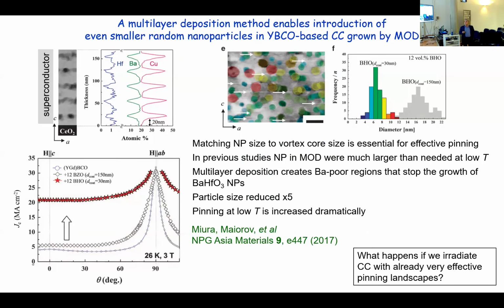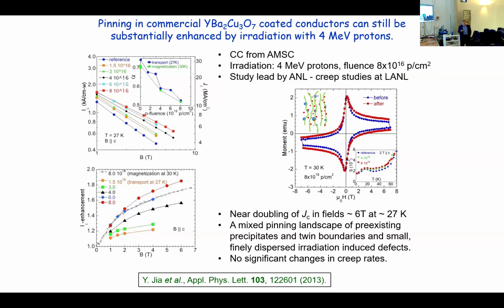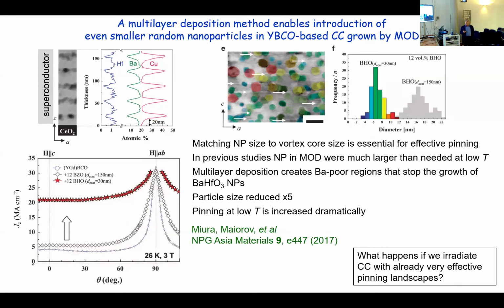But then Boris and Masashi Miura figured out a way to grow some kind of multilayer structure and introduce barium hafnate nanoparticles that they could make even smaller, 5 times smaller in size. And then they were able to improve dramatically the critical current at low temperature. So we understand a lot of how pinning works in these materials, and how we can correlate the kind of defects that we introduce with the properties that are obtained.